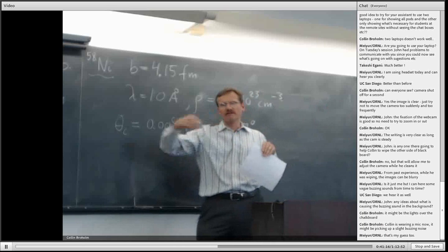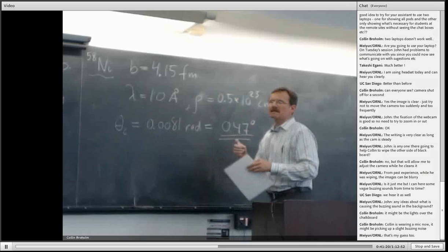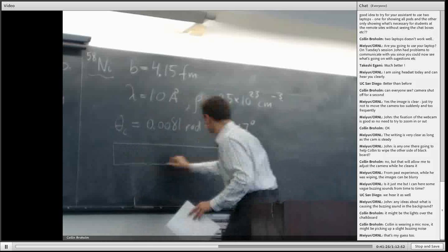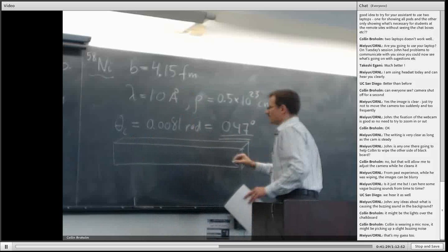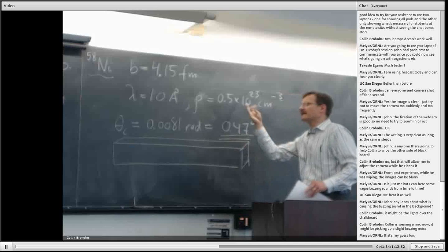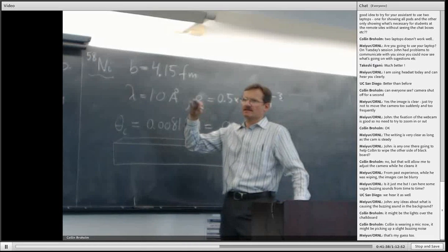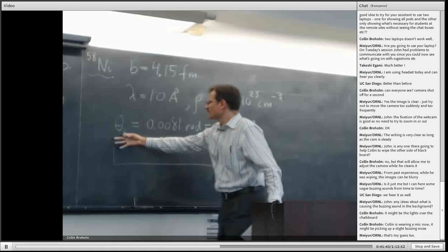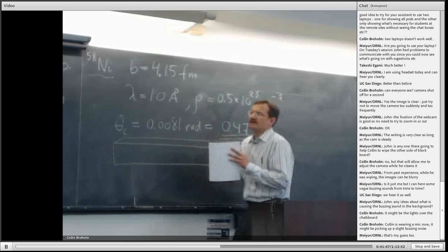Neutrons are simply traveling through this total external reflection process in a neutron guide, which is basically a very, very long tube, evacuated. It could be made from glass, coated on the inside by nickel-58, or it could be an even more ingenious combination of thin film structures to enhance the critical angle for total external reflection and to allow a large angular divergence to be transported through this guide.